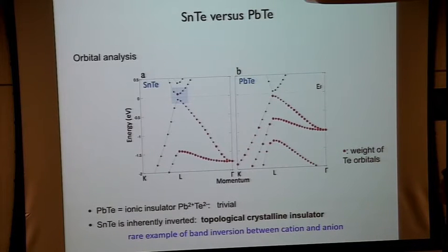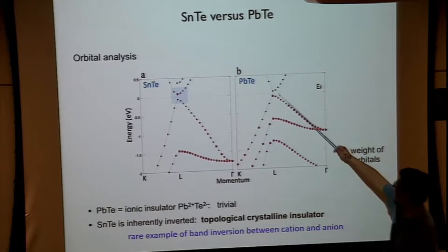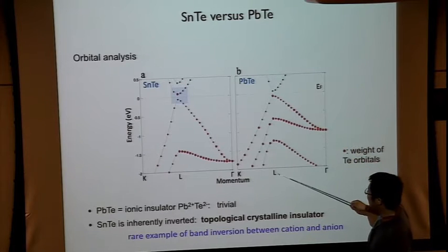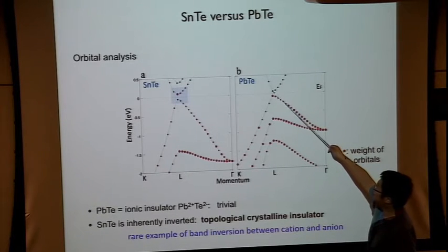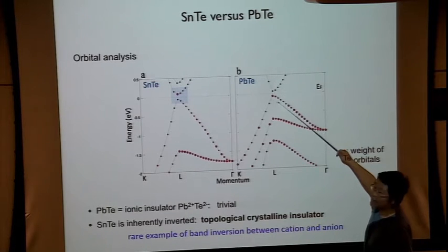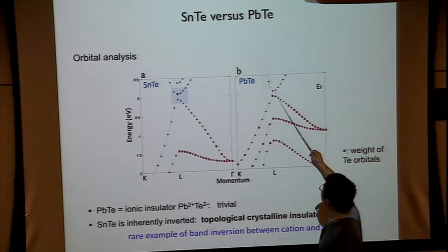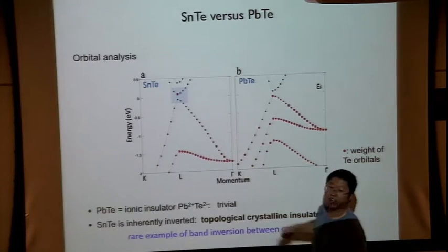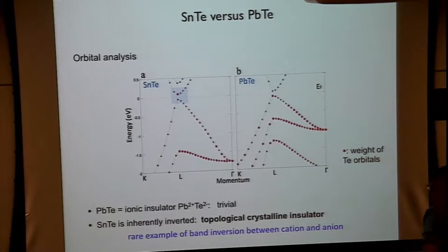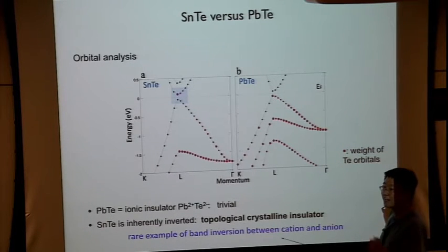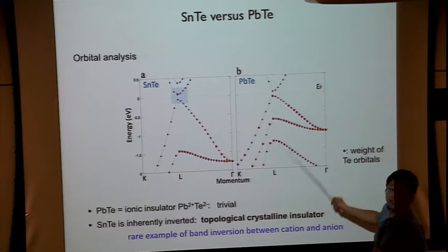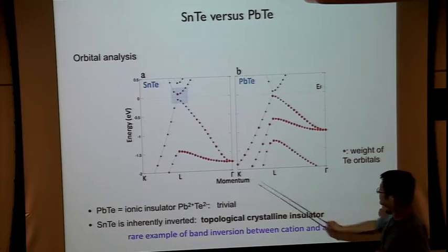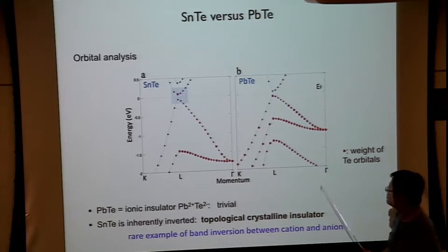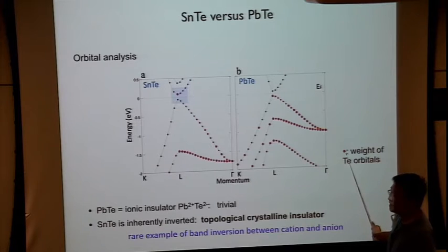So for that, we look at first principle calculations. This is the actual band structure in the vicinity of the L point, and you see that conduction and valence bands come close to each other, forming a massive Dirac fermion dispersion. This dispersion for lead telluride is very similar to tin telluride, but the difference is that the sign of the Dirac mass is opposite in the two cases. To infer the sign of the Dirac mass, we need to look at the wave function of the Bloch states in momentum space. These K, L, gamma are high symmetry directions in momentum space. Here, the size of the red dots denotes the weight of the wave function on the tellurium orbital.